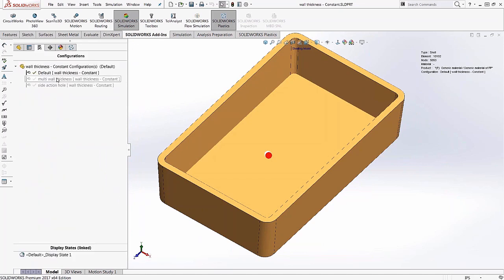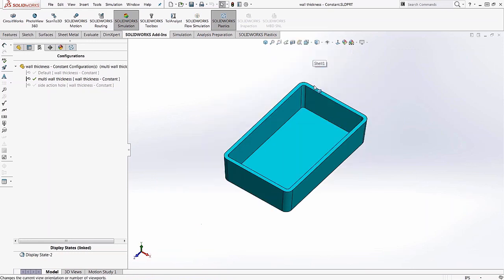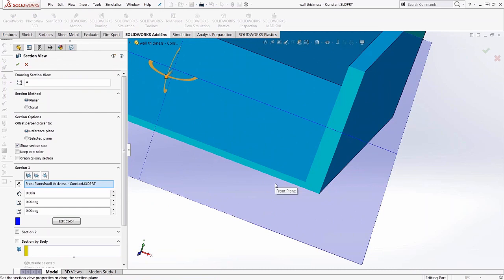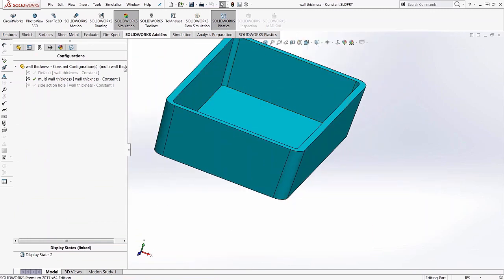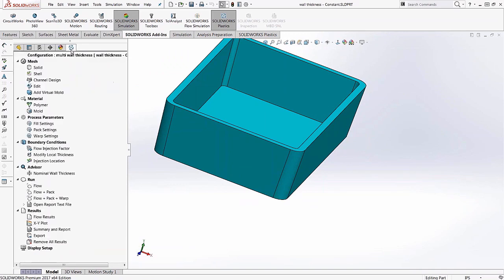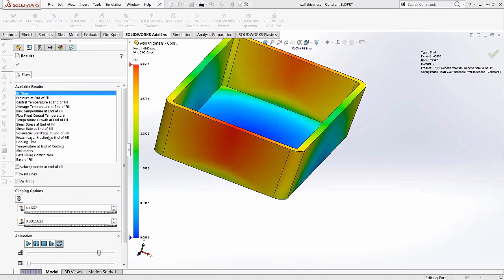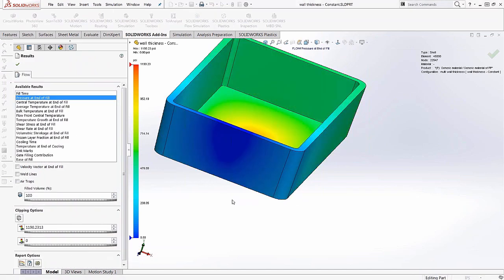Switching to a multi-wall-thickness design, you can see the differences in cross-section thickness. Looking at the pressure at end of fill, it has gone up almost three times compared to the uniform design. This can lead to short shots, where the current machine doesn't have sufficient pressure for the thinner regions, requiring a bigger machine.